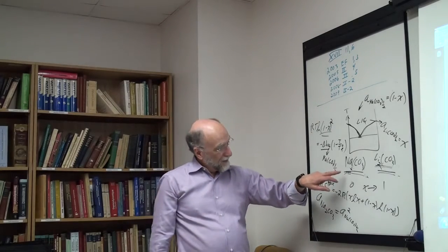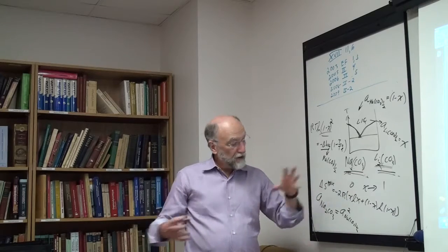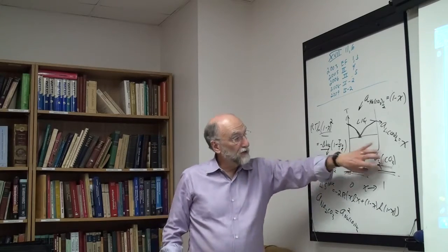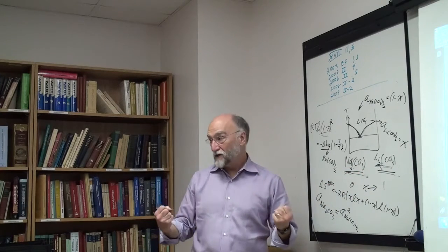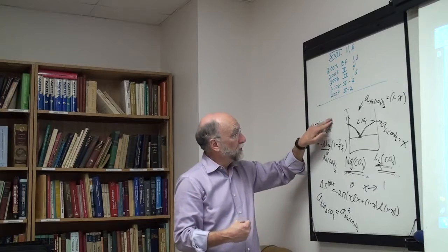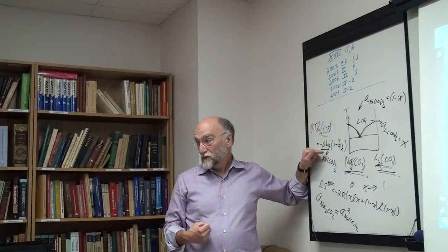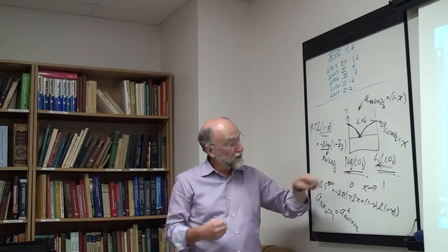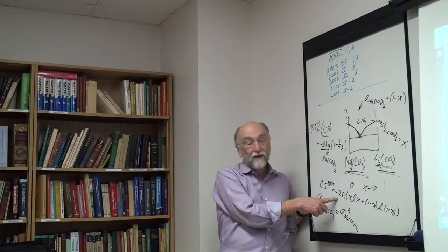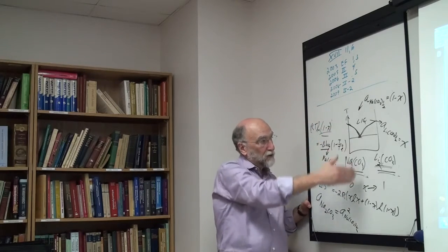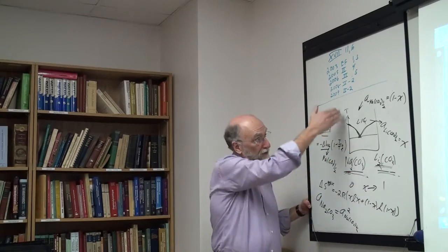Do the 2 sodiums and the 2 lithiums go in as independent particles, or do they go in as, say, a molecule? If this was a mixture of molecules, if this was Na2CO3 mixing with Li2CO3 molecules, which it isn't, then you would do it the old way. You would have 1 minus x, and this would be the heat of fusion of Na2CO3. But this forms two particles of sodium, which are independent. This forms two particles of lithium, independent, so you've got twice as much entropy. So you're getting twice as much Gibbs energy for every mole that you add. So it lowers the liquidus.